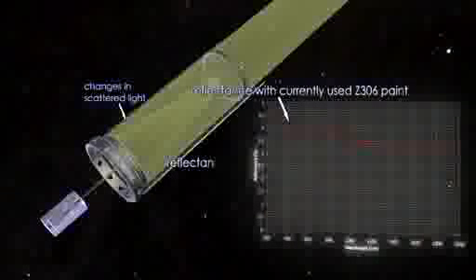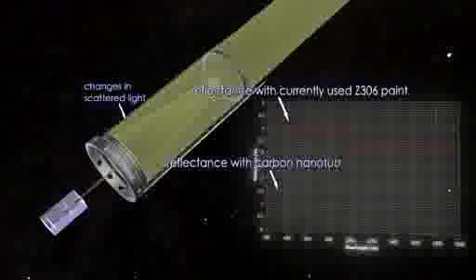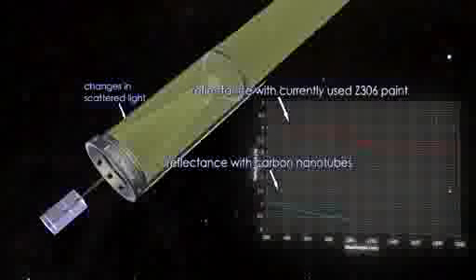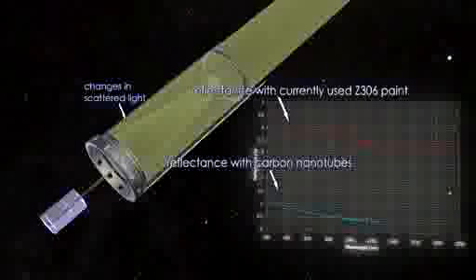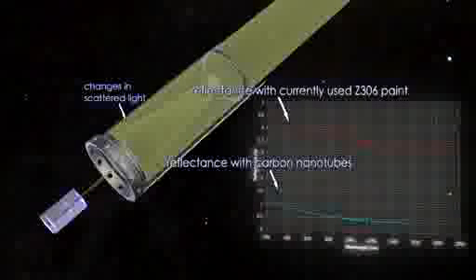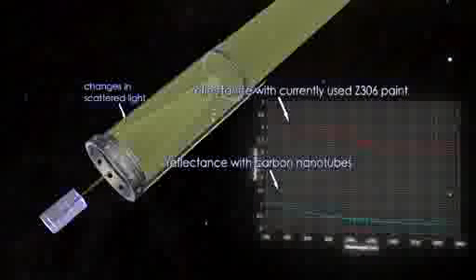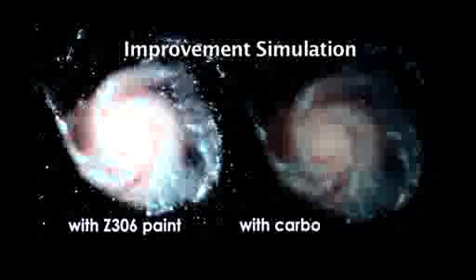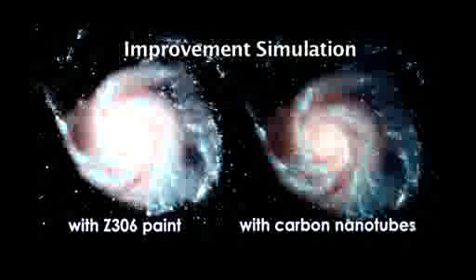Over the course of our work, we were able to optimize the carbon nanotubes to make them ten times darker than the paint. You could get a better observational efficiency. You're not throwing away 40% of your data.